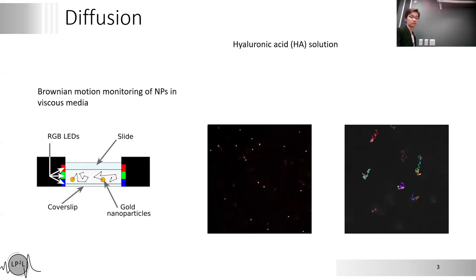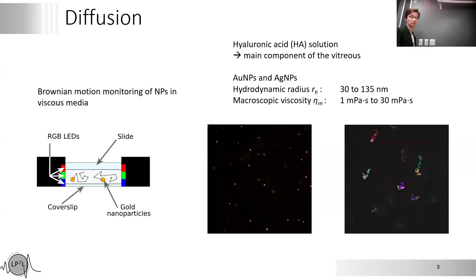So I did that for hyaluronic acid solution because it's the main component of the vitreous, and for gold and silver nanoparticles, for a wide range of hydrodynamic radius and almost two orders of magnitude for the macroscopic viscosity.